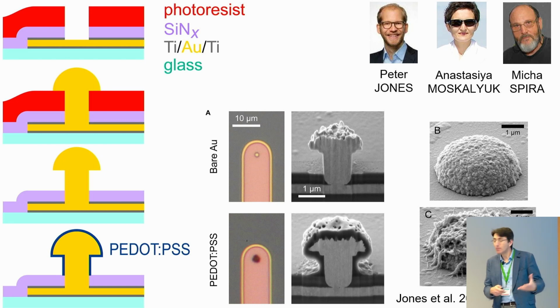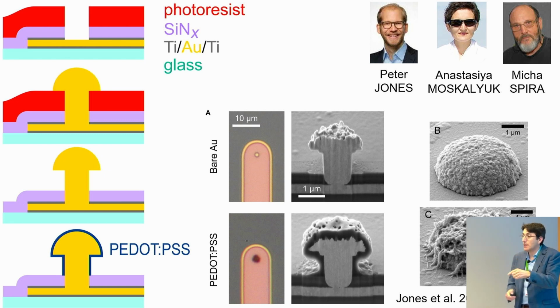And the main problem is that having 1 micrometer small electrodes made their electrical impedance very high. It was gigaohm high. And this clearly required some trick, particularly coating with PEDOT or PEDOT carbon nanotubes.